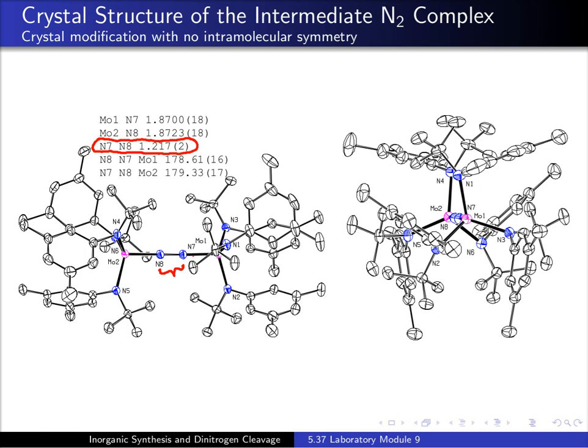And you see two views of it. In this end-on view, and also in the side-on view to some extent, you can appreciate that the Mo-N-N-Mo tetraatomic core in this system is essentially linear, and that there is also essentially a threefold axis of rotation. So you have a C3 axis in this system, and that leads to orbital degeneracies. And that in turn is going to help explain why this system actually has two unpaired electrons.